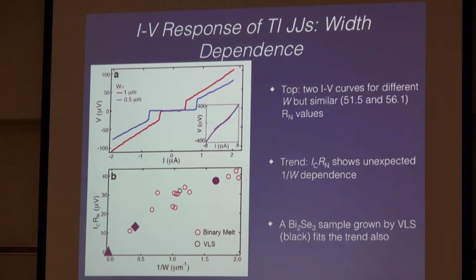Usually how you quantify the behavior of a Josephson junction at DC is you look at the product of this value of current where the resistance jumps up, that's called the critical current, times the normal state resistance. And in conventional Josephson junctions, that product is related to the superconducting energy gap that you induce in the sample. What was kind of interesting and new in this device, and something that we still don't really have a good handle on what's giving rise to, is that this ICRN product, which should just be a function of the energy gap you induce in the system, has some geometric dependence, which our initial thinking was that it has something to do with the length of the Majorana wire. I'm not sure that's relevant, but anyway, we observe something that's anomalous.